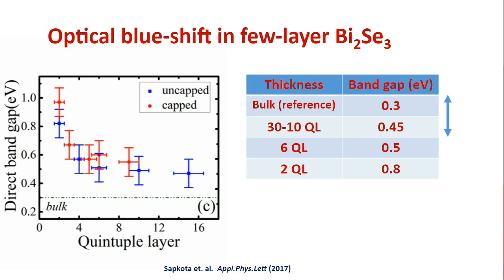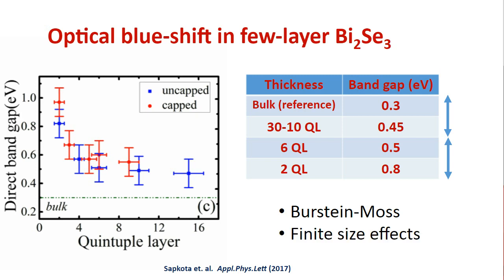We came to the conclusion that no, this is not a systematic error. This is another effect that's happening in our films called the Burstein-Moss effect, and I'm going to explain very quickly what that is in a bit. And the second effect is the finite size effect, right? That's what we were expecting in bismuth selenide. So as you go from 6 to 2, the band gap changes from 0.5 to 0.8. Again, a small change in absolute terms, but this is a 60% jump, right? Again, the height of a person does not change by 60% abruptly. So this is a huge change, and that is due to the finite size effect. So combined Burstein-Moss and finite size effects are giving us both these changes.